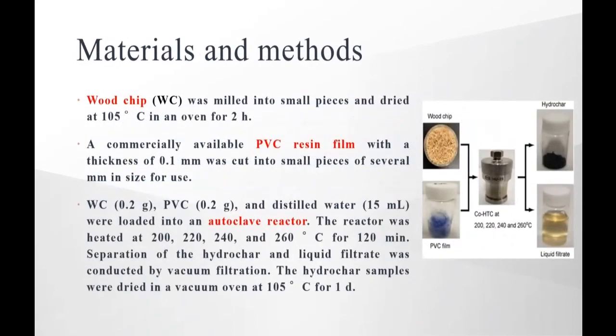This slide indicates the experimental procedures. Wood chips were milled into small pieces and dried at 105 degrees C in an oven for 2 hours. A commercially available PVC resin film with a thickness of 0.1 mm was cut into small pieces of several millimeters in size for use. 0.2 gram of wood chip, 0.2 gram of PVC, and 15 milliliters of distilled water were loaded into an autoclave reactor.